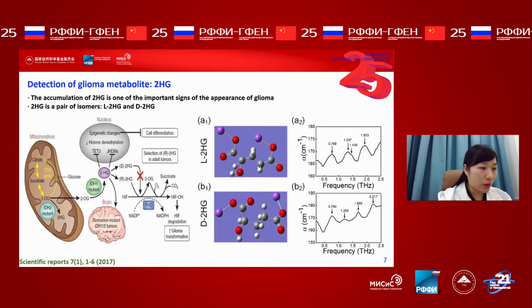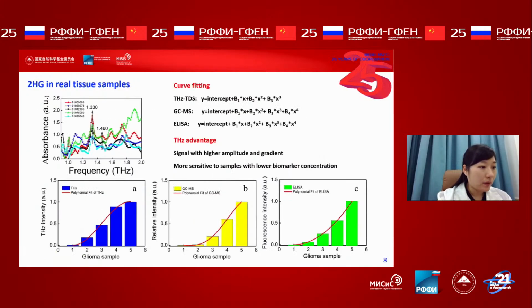Therefore, we try to use terahertz spectroscopy for analysis. Firstly, the vibration and the rotation of molecules are simulated by Gaussian software. The molecular structures are shown in Fig A1 and B1. The simulated terahertz spectra are shown in Fig A2 and B2. We can see that they all have 4 characteristic peaks, but the 2 peaks in the middle are different. So these theoretical differences tell us terahertz spectrum can be used to distinguish the isomers of 2-HG. Next slide, please.